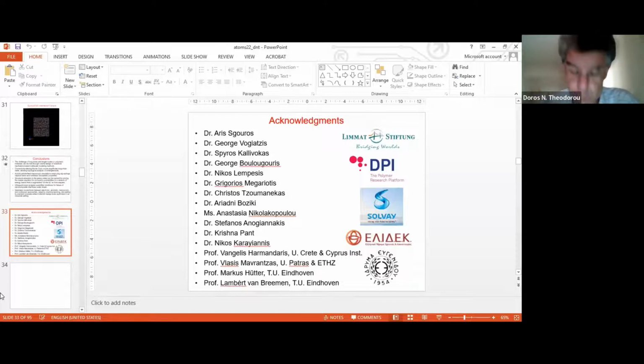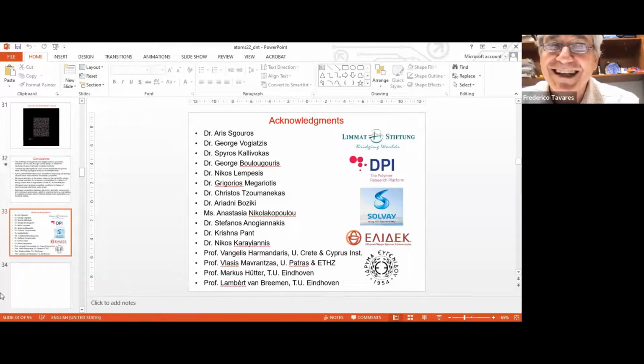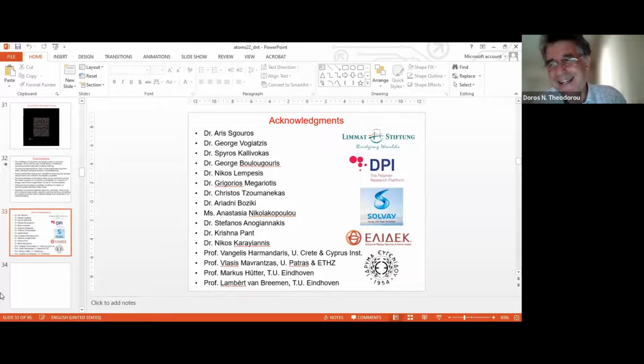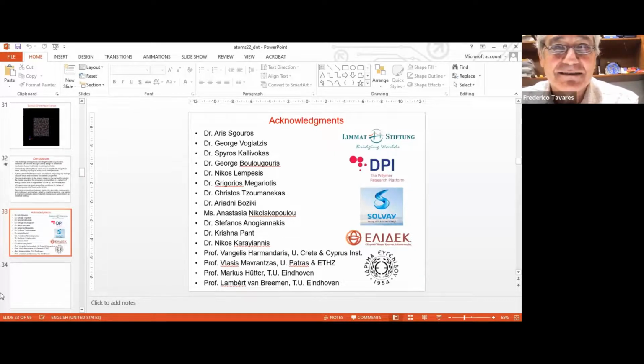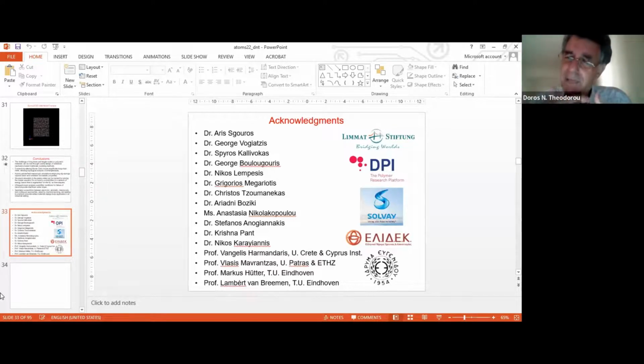Now, at the mesoscopic level, which is a very important question, really the way we do it here is we rely on an equation of state model. In other words, for this polyethylene, we use the Sanchez-Lacombe, which is quite good if you fit it. It has 3 parameters. Simple, but okay. It's very simple, yes. And then if you have a blend, then you would also have a free energy for the blend as a function of the composition. And that is the way you would go for a blend. We are now trying to really extend this to multi-component polymer systems. So this is the way we go about it.